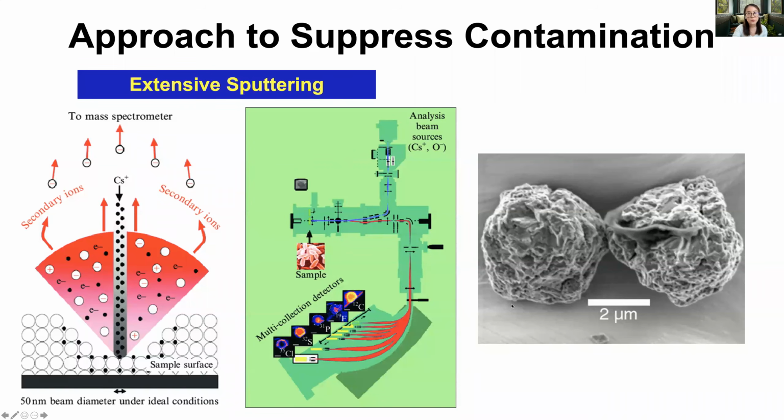In principle, we can circumvent the problem of surface contamination by doing extensive sputtering in the NanoSIMS instrument using the cesium beam, which can remove the surface material, the surface organic gunk, I mean, and expose the interior clean surfaces for our carbon and nitrogen isotopic analysis. Recently I did such tests, and we will see in the next slide what we get by purposely removing the surface material.